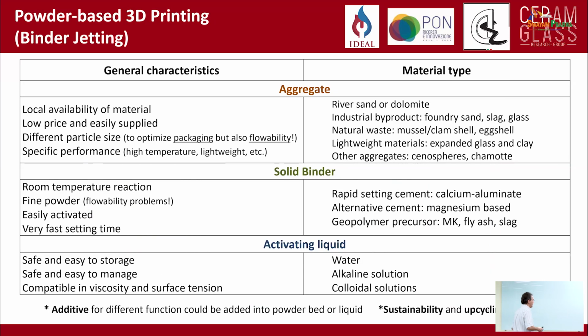And let me mention that because of the size of the nozzles, we can not only have an alkaline solution, but we can also have a colloidal solution. And this helps in closing some of the porosity inside the printed part. So we can get a much higher density with respect to conventional binder jetting approaches.